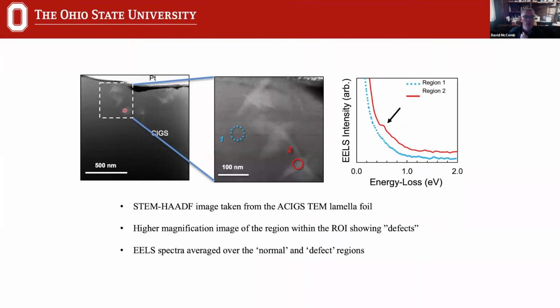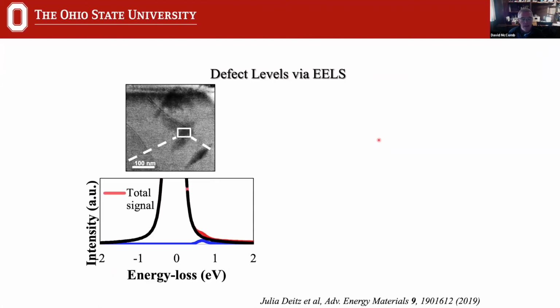So we'll lift out that FIB foil and put it in the TEM. We can see in the contrast that we can identify some regions where we have defects and regions without defects. When we look in the defective region, there seems to be some additional intensity, in red here, associated with the defect that's absent in the normal region. So using a similar approach, because it's a defect region, we can add our spectra together from that region and get better statistics in our energy loss spectrum. Now we can fit our zero loss peak much more carefully and precisely, because we're only dealing with a single spectrum, not an entire array of spectra.